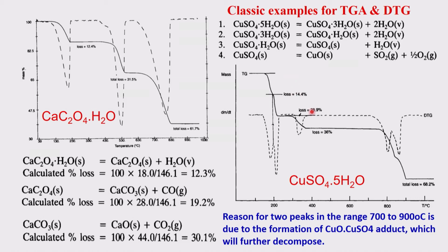So, 14.5, 14.5, 29, and the next one is 1 molecule. So, there will be half of it, so it will be around 7. So, 29 plus 7, and that is around 36, you can see that. So, that means 2 molecules of water, 2 molecules of water, and 1 molecule of water.